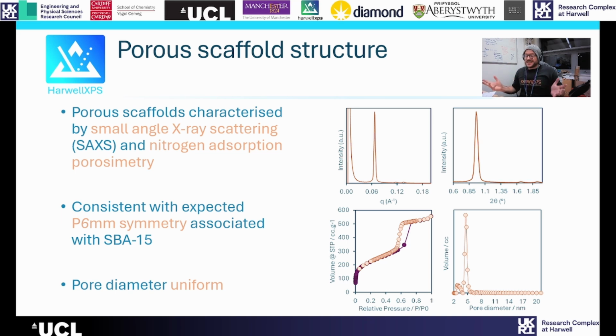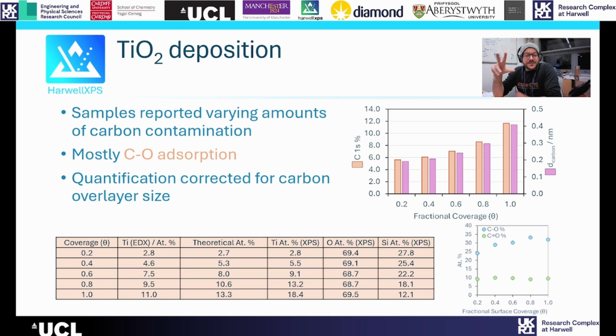And we should probably start with the silica framework substrate, just to make sure that our material is exactly what we think it is. Small angle X-ray scattering and nitrogen adsorption porosimetry confirmed our base structure was as expected. So then we can move on to our titanium modified materials. Quantification is probably where we should start, right? Because we need to know exactly how much of our active sites we have.